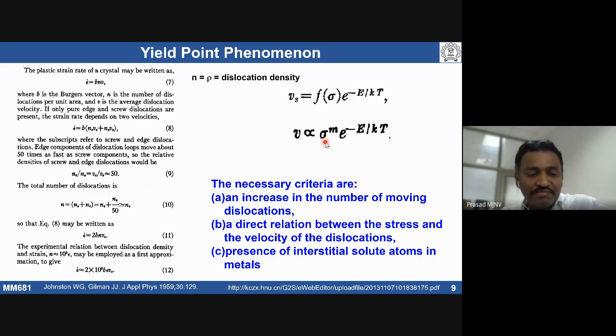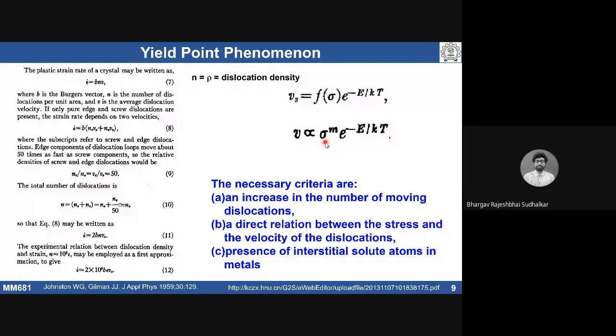Because if the dislocation density increases, I need more and more solute atoms for complete locking of the dislocations. So if I take two materials, one fully annealed and the other heavily cold worked, same material, say mild steel, what does that mean? Annealed material means a certain dislocation density. What is the typical dislocation density for annealed materials? Any idea? A student answers: 10 raised to 6.